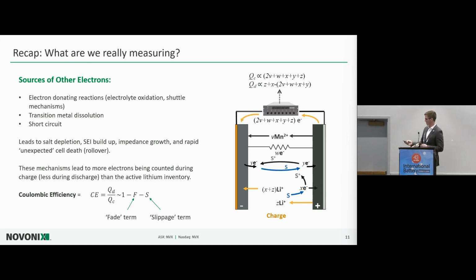And so all of this during charge, we're counting all this extra capacity. During discharge, all of these mechanisms act like self-discharge, basically. So we're counting all this extra charge capacity. We lose some discharge capacity into these invisible self-discharge mechanisms, and that also decreases our coulombic efficiency. So now we've got these two separate terms to coulombic efficiency that, if we can really measure what's going on in our cell accurately enough, we can start to split up some of these families of different degradation mechanisms.